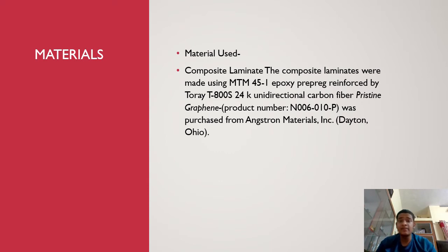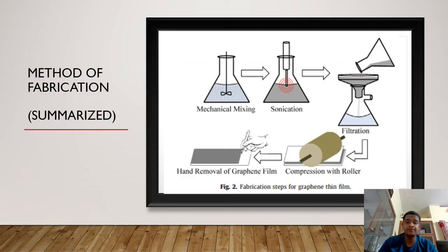The materials we have largely used are composite laminates and a variety of coatings using pristine graphene. In our method to fabricate these panels, flexible GTFs made of pristine graphene were used, using a process involving mechanical mixing, sonication, filtration, compression, and removal.